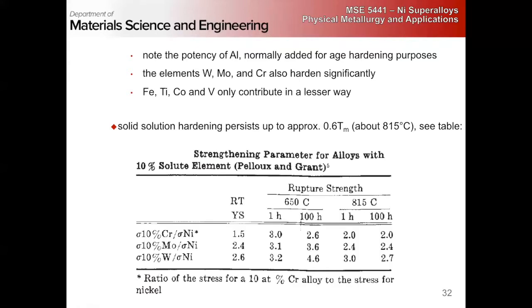Right? And this solid solution strengthening is going to persist to about 0.6 of the melting temperature, about 815 C. After that, we have just too much thermal activation, right? And it's easy to get around, right? There's not a whole lot of interaction between the dislocations and the solid solution strengthening anymore.